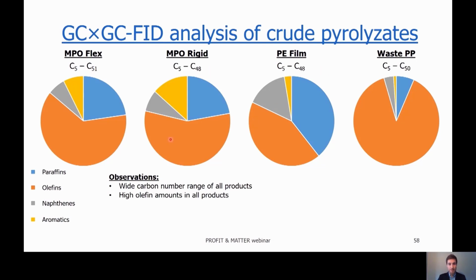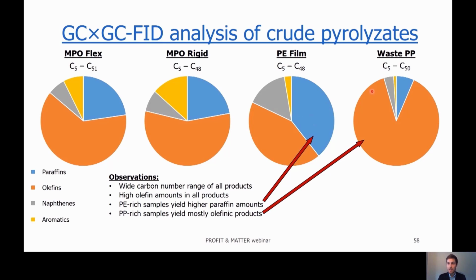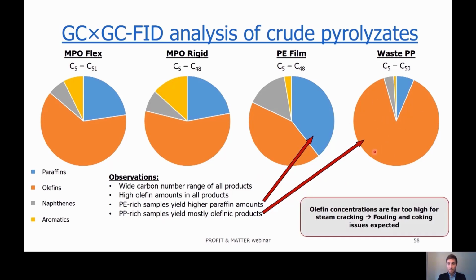We can see right away that all of them have a quite high olefin concentration, so the orange parts of the pie charts are quite large for all of them. What can be seen, however, is that the PE-rich sample, PE film, which mainly consists of polyethylene, yields higher amounts of paraffins, while the PP-rich waste PP pyrolysate yields a significant amount of olefins, almost entirely consisting of olefins.